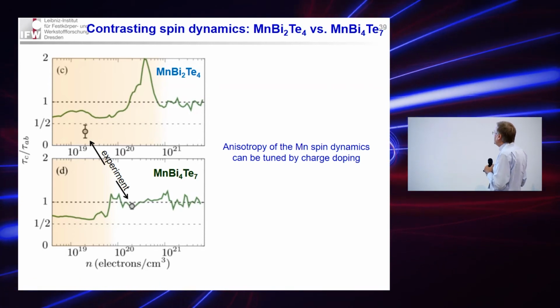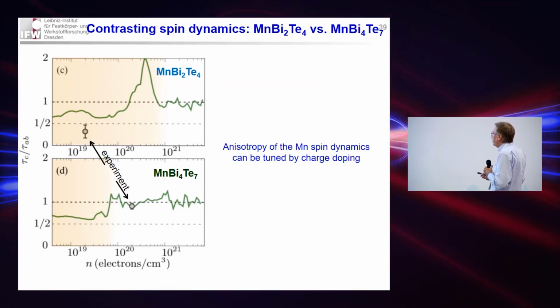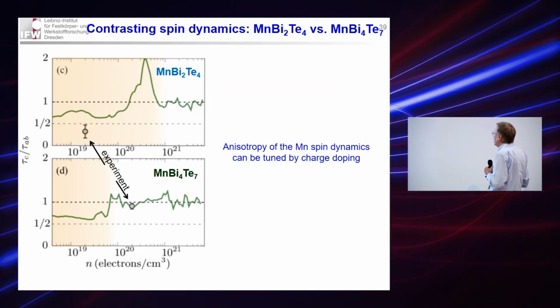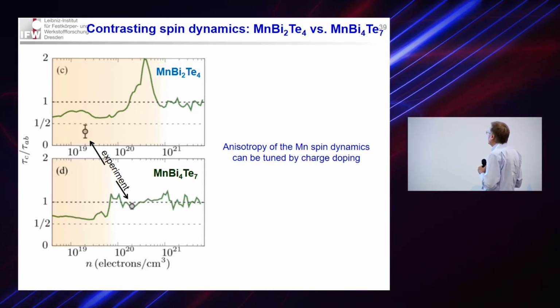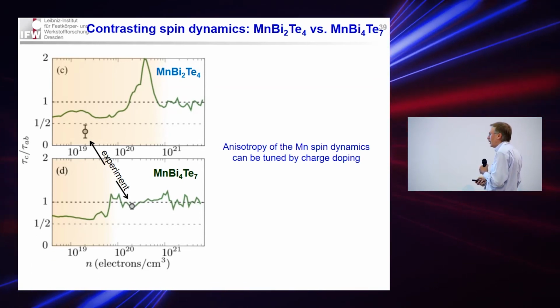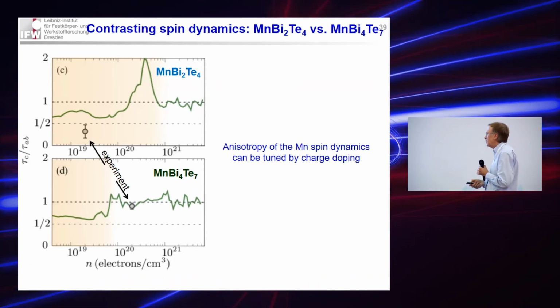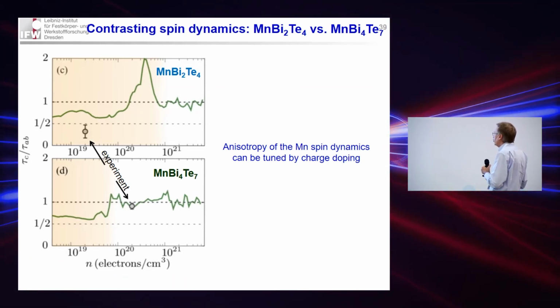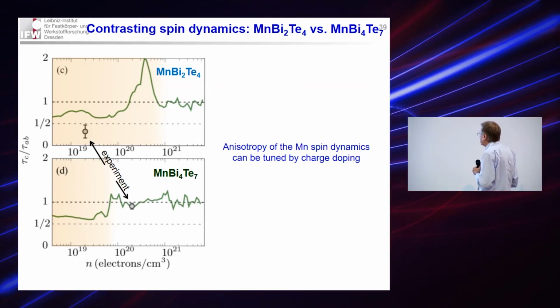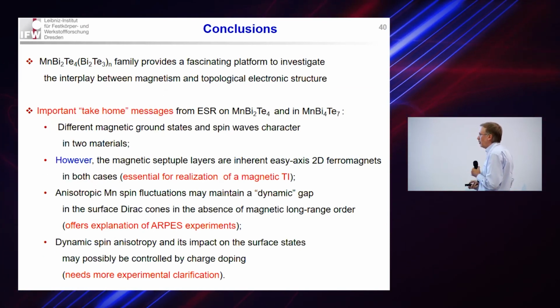So this, our first experimental observation, and also the theory predictions, suggest that the anisotropy of the manganese spin dynamics and its impact on the surface states could be controlled and tuned by charge doping. So this brings me to my conclusions.